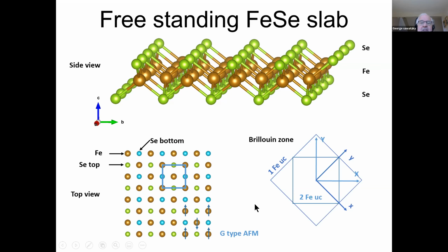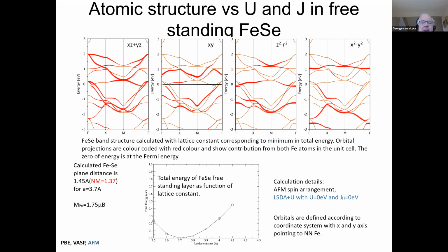Okay, so let's go and have a look at this. This shows you the density functional calculation just in an LSDA calculation. And it's relaxed. And if you do LSDA, you actually find, and this is G-type, this is not stripy, this is G-type. Now, for many of these things, as far as lattice constants versus magnetism is concerned, the magnetic order really doesn't matter so much. What matters is whether or not you have a local moment.